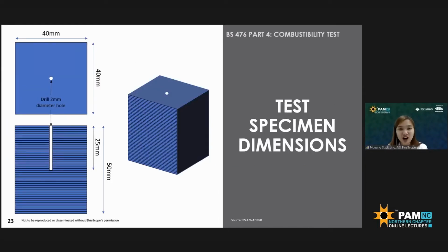And this is how the test specimens will be prepared for the combustibility test. The test specimen is required to be prepared in 40 by 40 millimeters square shape with 50 millimeter height. And it is required to drill a 25 millimeter depth because it is required to insert the thermocouples inside the test specimen.